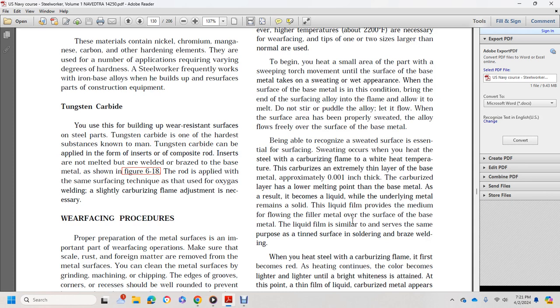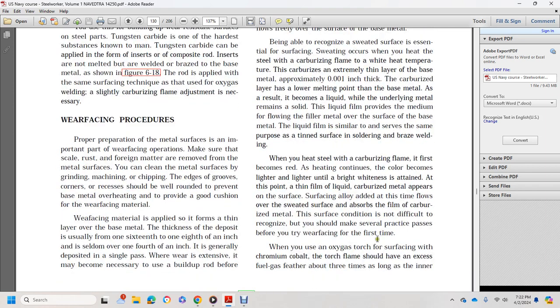The liquid provides a medium for flowing. The filler melts all over the surface of the base metal. The liquid film is similar to that used in brazing and bronze welding. When you heat the steel with a carburizing flame, it first becomes red. As heating continues, the color becomes lighter and lighter until a bright white is attained. At this point, a thin film of liquid carburized metal appears on the surface. Adding more time allows an oversweated surface to absorb the film of carburized metal. The surface condition is not difficult to recognize, but you should make several practice passes before you try wear facing the first time.